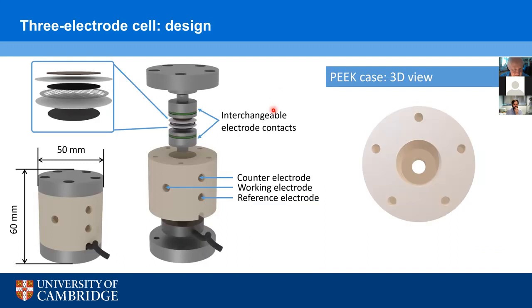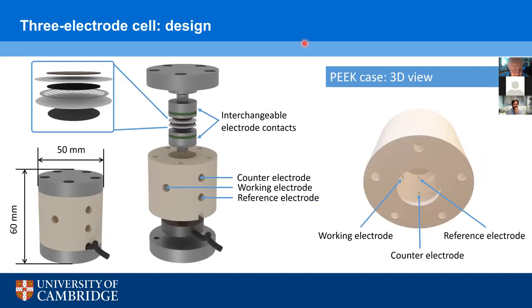Okay, so looking at the design of the 3-electrode cell, it's a cylindrical external holder made from PEEK, which is electrochemically inert and also chemically inert to the different electrolytes that we're using. And this contains the 2 electrode contacts, which are made from stainless steel, which is again electrochemically inert and doesn't participate in the electrochemical reaction at all. We can then apply pressure through the 2 caps, which are shown at the top and the bottom. And then at the bottom of this image, you can see the sensor with the black cable coming out of it, which doesn't have to be installed when we're assembling the cell inside the glove box. So we don't have to put it through the vacuum chamber during assembly.